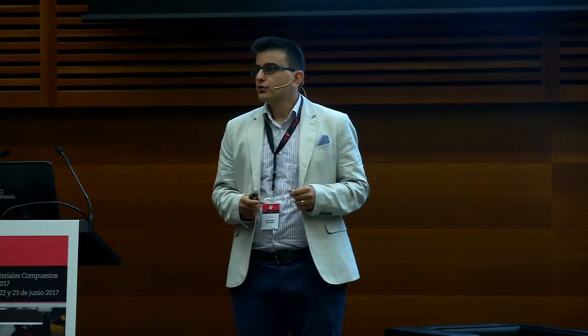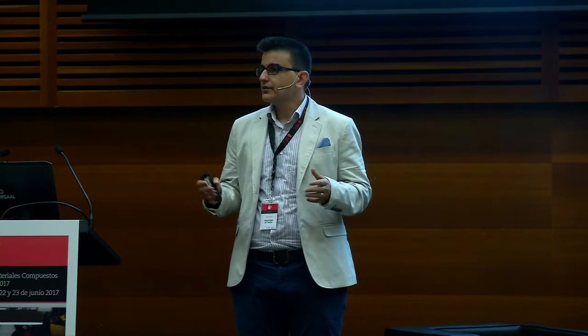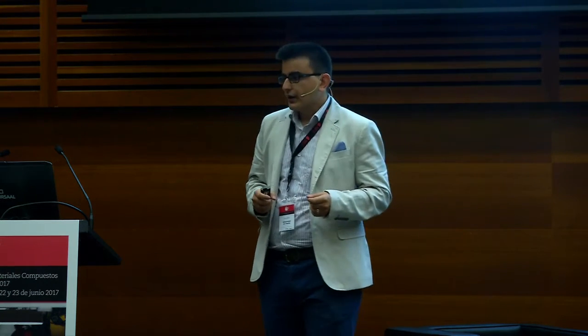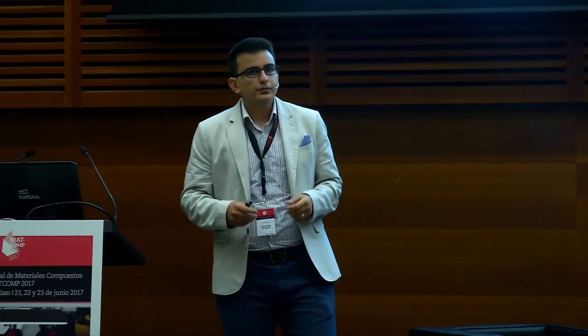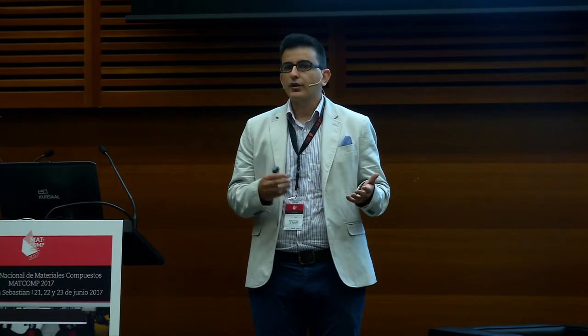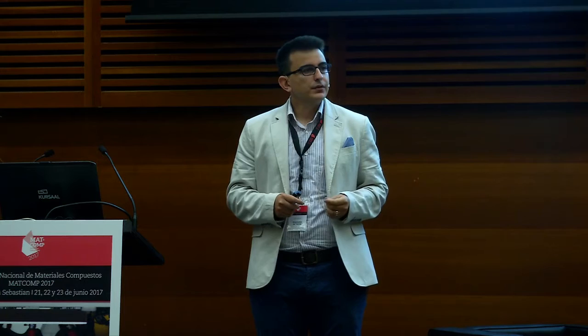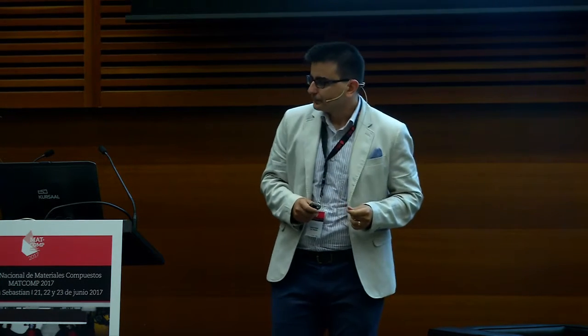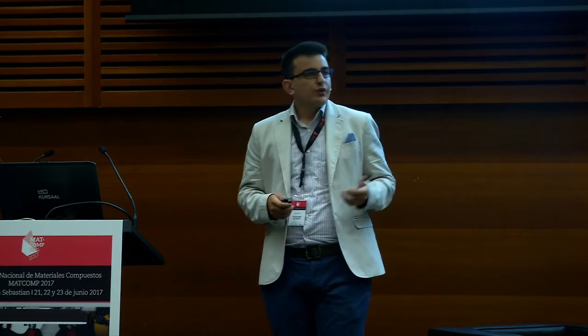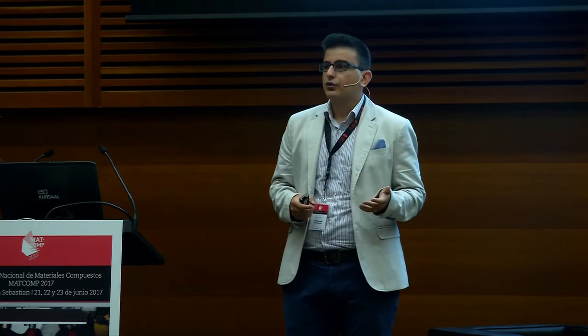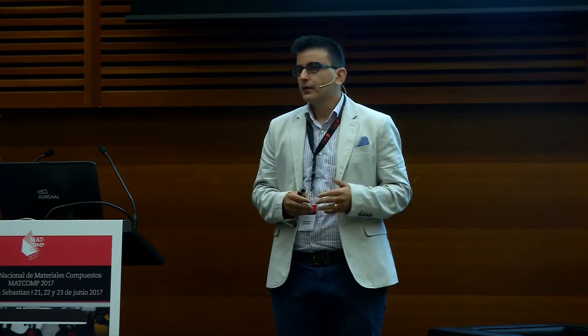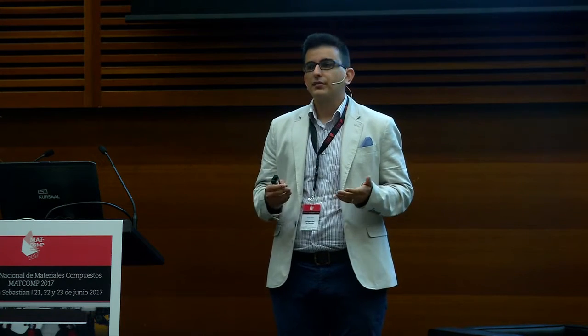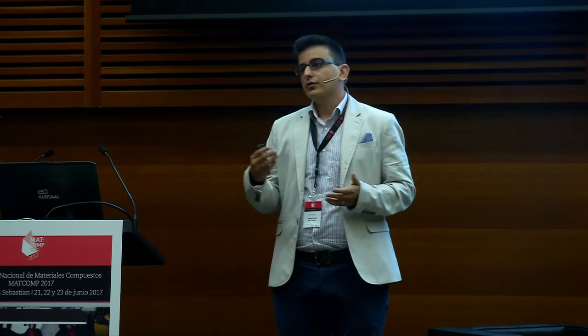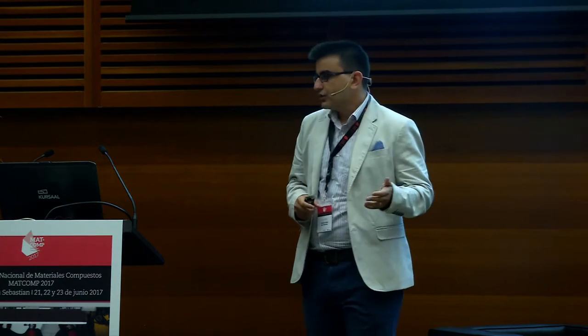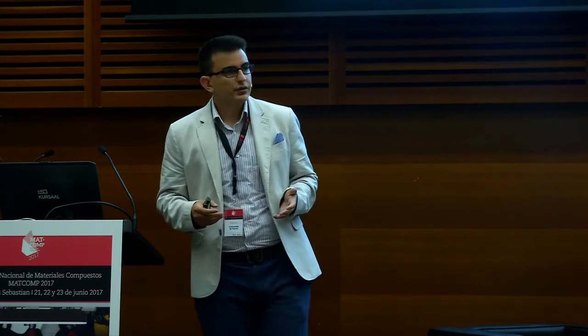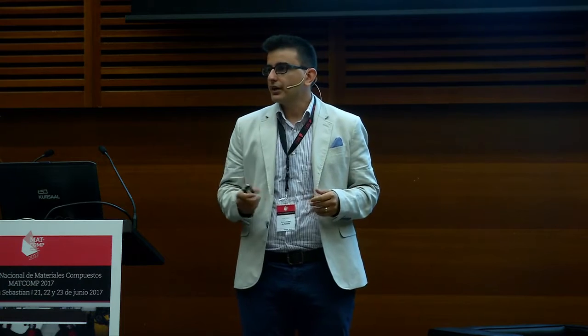Usually a mold is used in which the fiber reinforcements are impregnated, and during the process stresses occur due to the anisotropic behavior of the ply in micro and macro level, as well as a competition between thermal and chemical shrinkage strains. So after the process, obviously we have the product, and usually in the product we have residual stresses which may cause matrix cracking or delamination, even in serious or in premature format. In addition, we may have voids, resin-rich areas or dry spots because of the poor impregnation, as you can imagine.